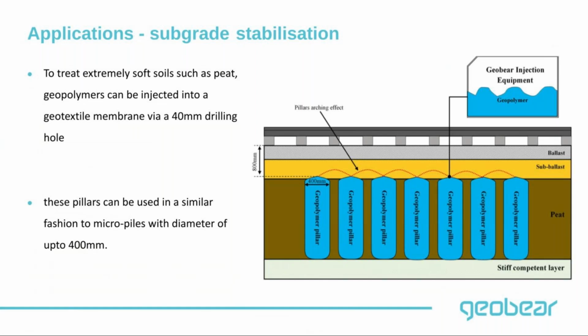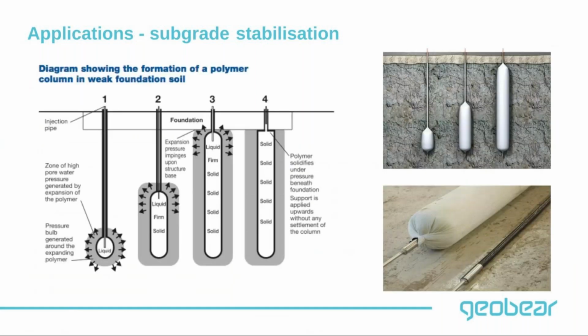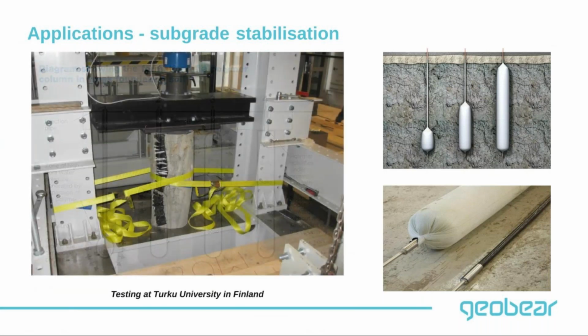Now, obviously, this kind of solution is reserved, as Levente said initially, for extreme situations, like when you've got engineering peat or some really soft material that normal injections wouldn't be able to deal with. So that's a very interesting way of dealing with it. And again, you're not taking anything out of the track. You're doing the injections in a non-disturbed way. This is how that pile structure looks. We call it power piles, and this is how it's injected and expanded into the ground. We've carried out some testing in Finland to understand the carrying capacity of these piles, and we found that their carrying capacity exceeds 200 kilonewtons.